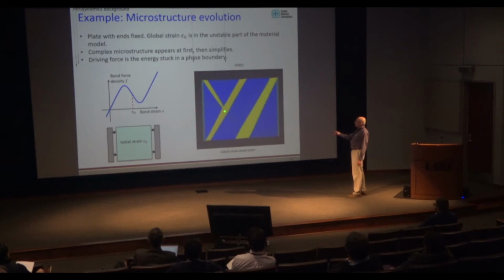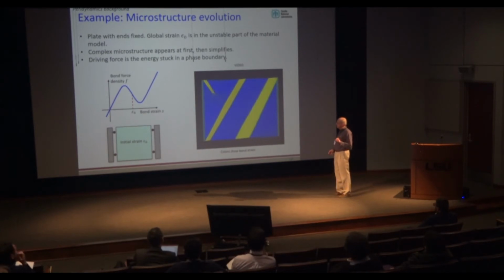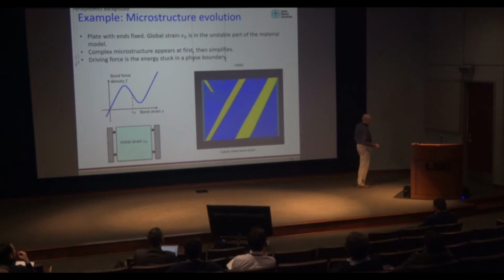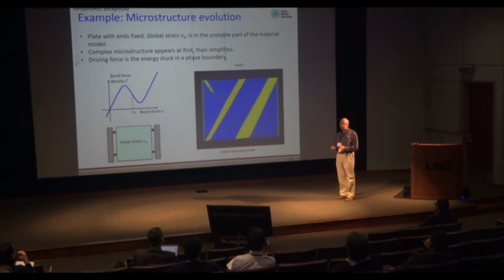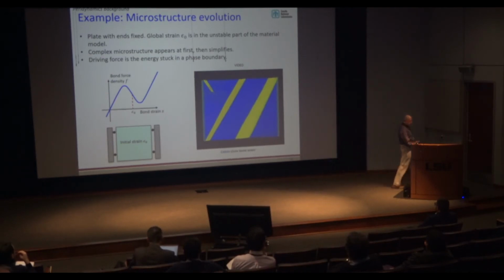These phase boundaries in peridynamics have a finite width, which is related to the horizon, and they also have a certain amount of energy due to the non-local interactions within this finite thickness of a phase boundary. So that additional energy per unit surface area provides a driving force for these phase boundaries to join up with each other and reduce their total surface area. So that is actually pretty similar to what happens in real life, where actual metal microstructures will very often evolve in such a way as to decrease the surface area of grain boundaries.